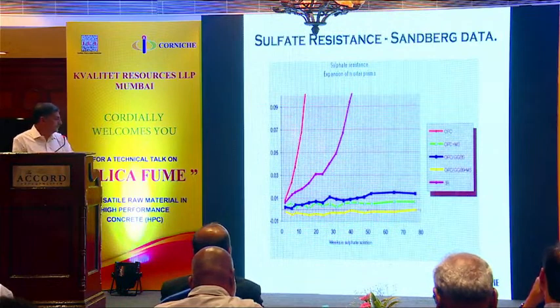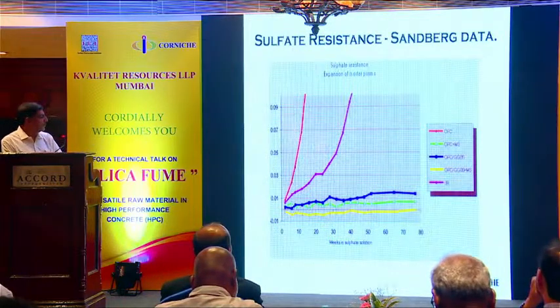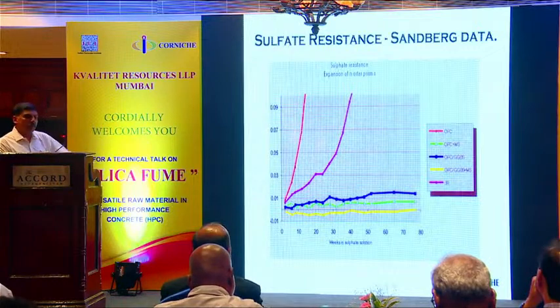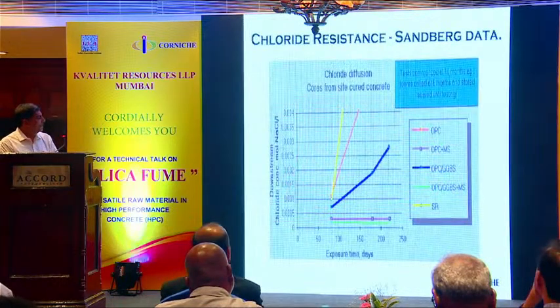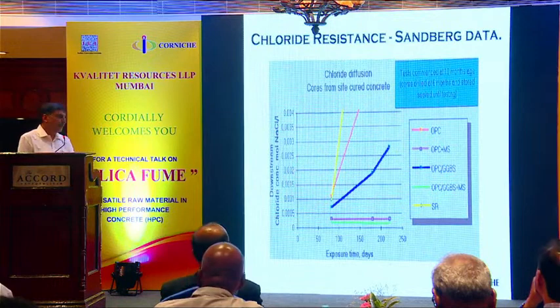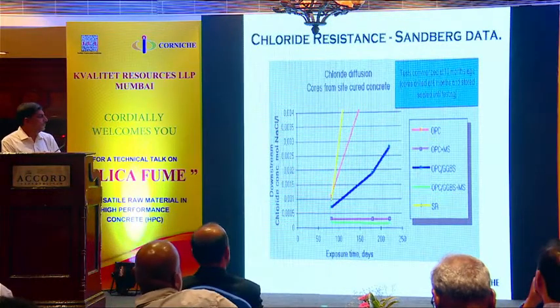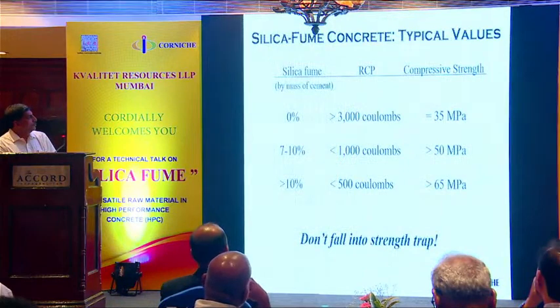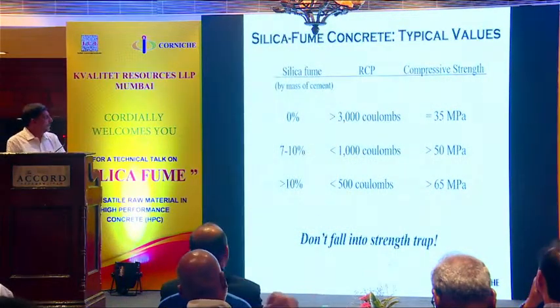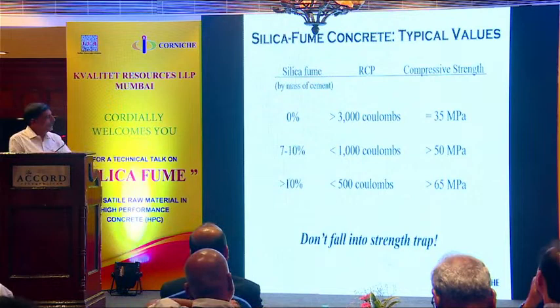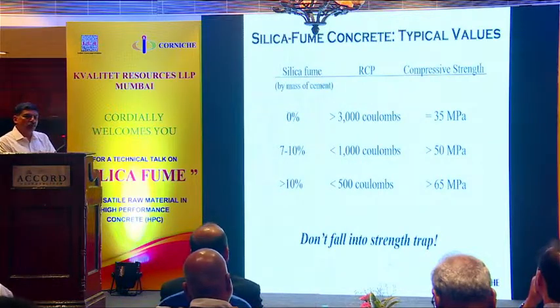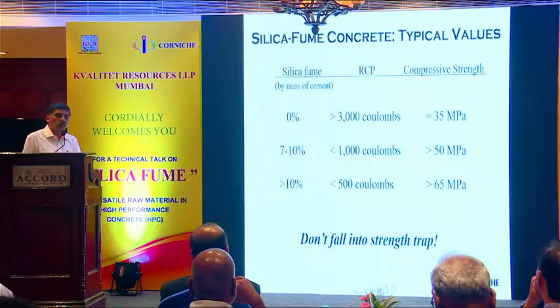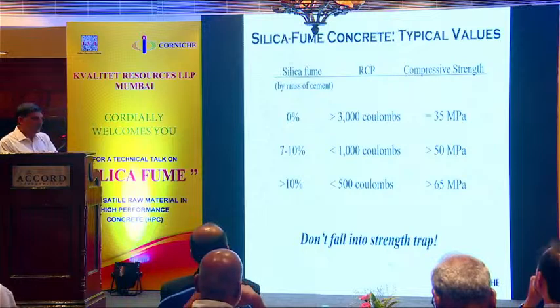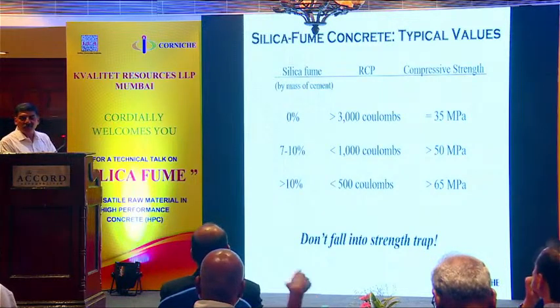Sulfate resistance, see, it's highly resistant to sulfate, silica fume concrete and ternary blends. Same is the case with chlorides. It resists sulfates and chlorides, both. So, silica fume concrete typical values, in fact, what we get, by adding 7 to 10%, you will be able to achieve less than 1,000 coulombs. About 10%, I now would not recommend, because, as Manu sir said, it just acts as a filler. And since we are importing it, it's a bloody expensive filler in India.